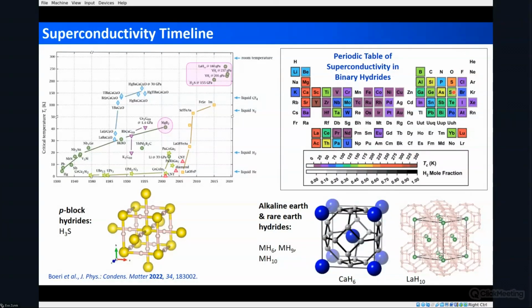And there are some other regions where you might have a high TC value, for example, H3S. And this table is a little bit incomplete. This contains both theoretical predictions and some experiments when they were available. And this was made a couple of years ago. And in the last few years, a number of theory groups have studied, for example, neptunium or plutonium hydrides under pressure. So I would like to point out that this H3S compound was actually made at about the same time that it was theoretically predicted, and the TC matched really well the experimental TC, the measured TC, and that was done in about 2015,